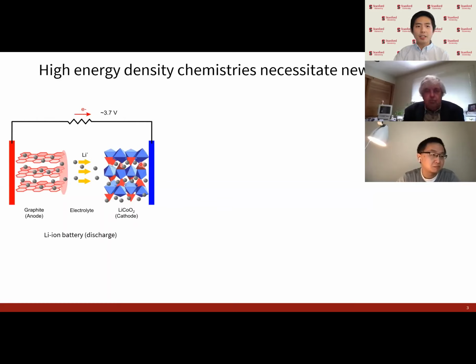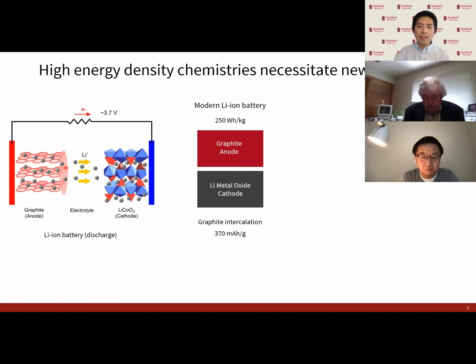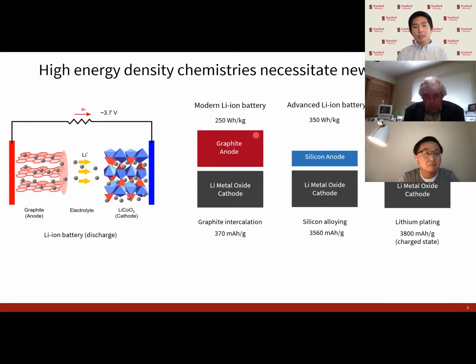Now on charge, lithium ions move through the electrolyte, which is typically some sort of liquid that conducts only lithium ions, and insert themselves into the graphite anode, where lithium ions are stored between sheets of graphene. By moving these lithium ions back and forth between the cathode and the anode, electrical energy can be stored and released on demand. Now, these modern lithium-ion batteries have energy densities of about 250 watt-hours per kilo. But by switching to anode materials that can store more lithium, such as silicon or metallic lithium, we can further increase our energy densities beyond 250 to about 350 with a silicon anode, and by moving beyond lithium-ion batteries, in excess of 450 watt-hours per kilo.